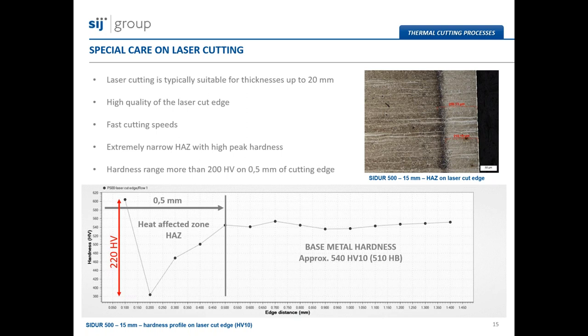And in this region, we can detect high peaks of hardness. For example, we have a 500 Brinell grade, and this grade can reach a hardness of more than 570 Brinell close to the cutting edge. And if we are doing an additional bending on those pieces cut from the plate, we recommend to remove the heat-affected zone with the angle grinder and also to use a larger bending radius for bending, as it is recommended in our datasheets.